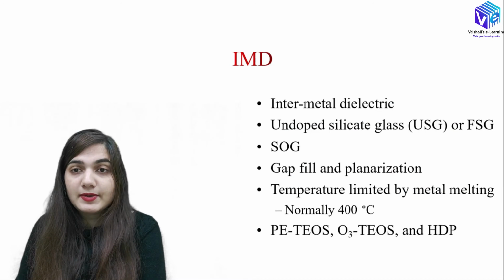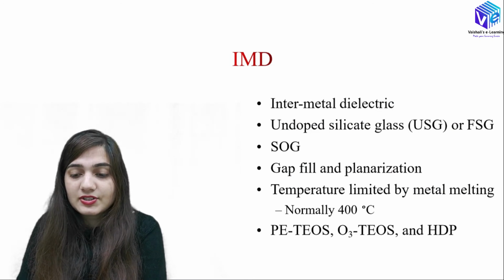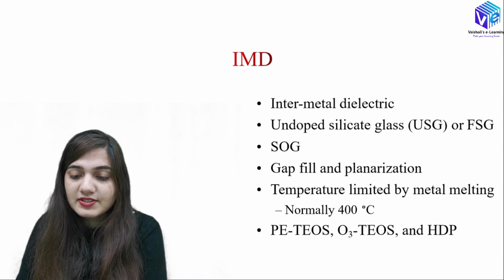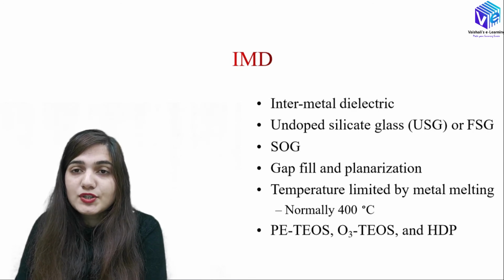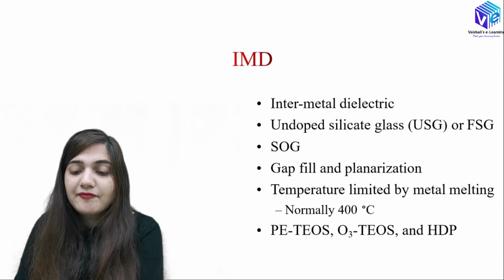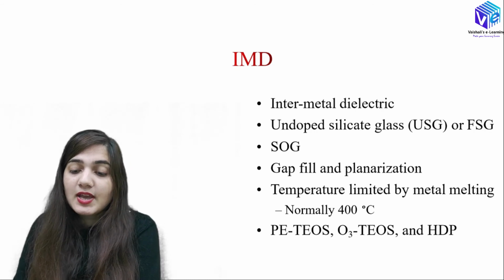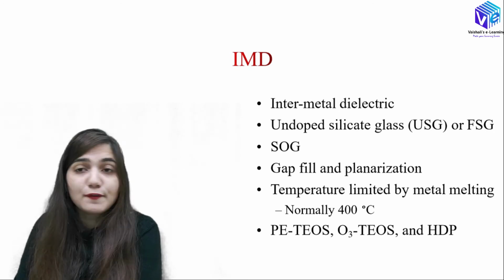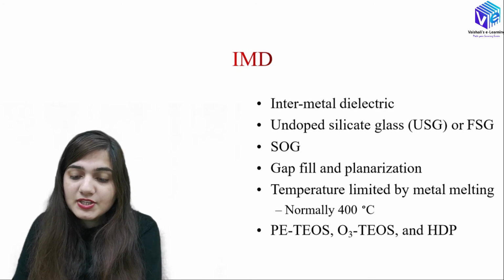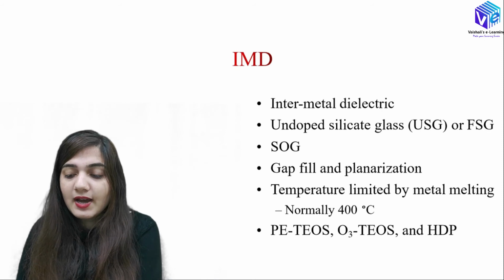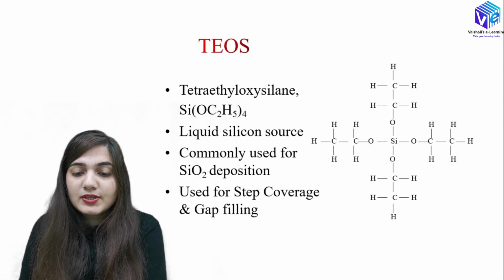Now coming to the IMD. IMD means the inter-metal dielectric. It is done with the help of undoped silicate glass or FSG. Here we are using a technology called spin-on glass. After that we use the gap fill and the planarization process. The temperature is limited by the metal melting, so the temperature is limited to around 400 degrees Celsius. We cannot process at a higher temperature than this. We are using plasma enhanced TEOS, O3 TEOS, and high density plasma as well. So what is TEOS?